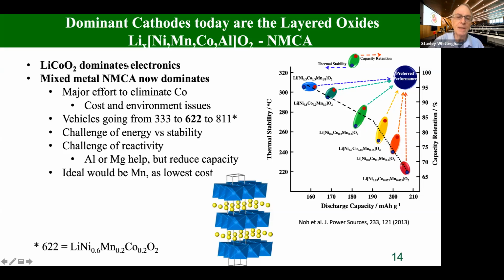And reducing the amount of cobalt means you've got to increase the nickel or manganese. And it turns out the reaction rates are poor if you increase the manganese. So most people have gone from an equimolar mixture of nickel, manganese, and cobalt to this 60% nickel. And I put the formula at the bottom here. And this is what's in today's vehicles. And the goal is to go to 80%. There's a big challenge here because the more nickel you put in these materials, the more unstable they are.